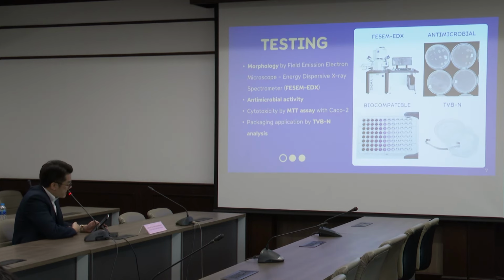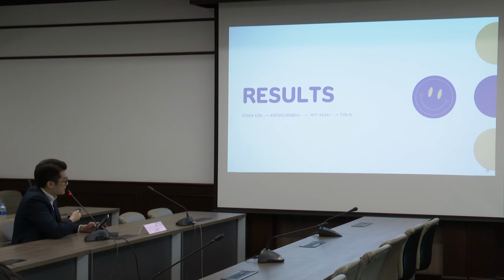Next we test various kinds of characterization. The first one is FESEM to examine the surface morphology and element composition of the nanocellulose hydrogel, then antimicrobial activity, and cytotoxicity by MTT assay to evaluate the toxicity of the nanocellulose hydrogel toward the Caco-2 cell line. And the last one is TVBN analysis to quantify the amount of volatile nitrogen compounds, which indicates the spoilage of the meat products. So let's move to the results.